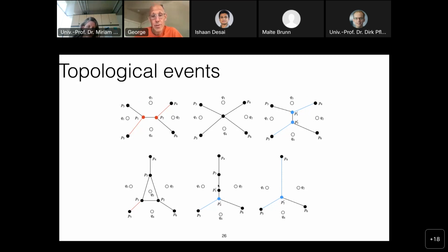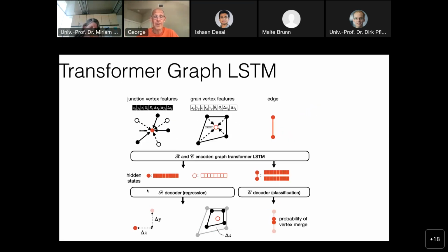So in order to capture them, we use two networks simultaneously. One network's job is to predict the motion of these vertices, and the other network gives us a probability for edges and grains disappearing. So it's a classifier. So we use both a regression and a classifier simultaneously in order to predict the evolution of the microstructure.